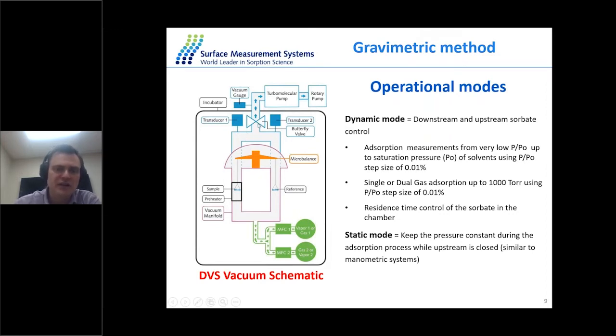When the set pressure is reached, then there's continuous feedback between the butterfly valve and the baratron. When the pressure goes above the set pressure, the valve receives the feedback and opens a little bit. So in that case, we flow in the vapors over the sample while we keep this pressure constant. And the butterfly valve exhaust is actually connected to the dry pump. So what it means, when the pressure is too high, the valve opens, the vacuum pump sucks out the molecules out of the system and the pressure is reduced. And this way, we can flow the molecules over the sample while we keep the pressure constant. At the same time, we continuously record the change in the mass. So we have this ultra balance here.